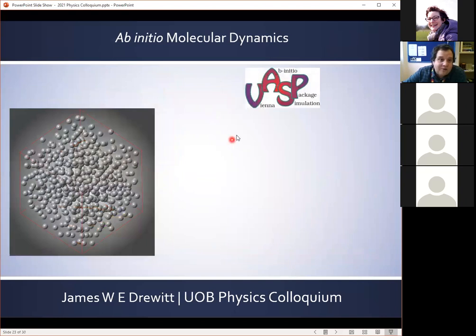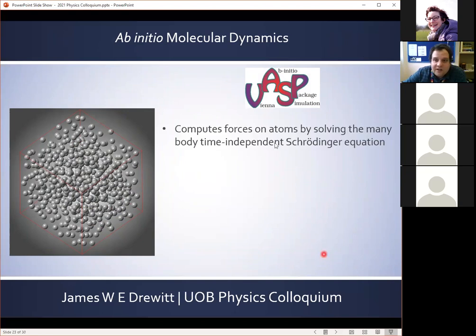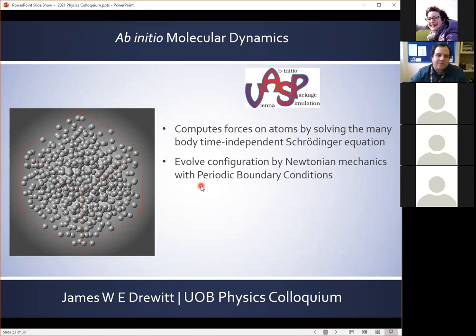And I combined these measurements with some ab initio molecular dynamics simulations. And so these use the VASP code, which I ran on Bristol's ACRC BlueCrystal 4 supercomputer. So ab initio molecular dynamics computes the electronic forces on atoms by solving the many-body time-independent Schrodinger equation. And at each time step, the atomic configuration is evolved using classical Newtonian mechanics.